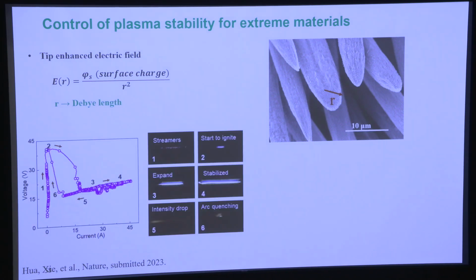So here is a design, and we design an electrode material. Now it's not a metal anymore. We tried using carbon fibers as the electrode material, with a diameter around 10 microns and a separation distance around 10 microns. So that's comparable to the Debye length we want.